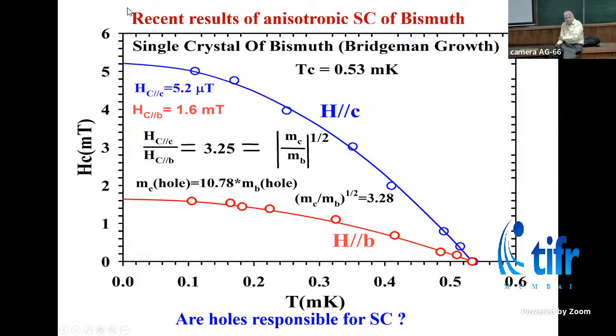What we have done in the last 2 years, I think before I took over as director, is the anisotropy. That was really hard because OHM has left. There was only one scientific officer with me, and we were doing the experiment. It took us 2 years to finish this part of the graph, which I told you about. So we see an anisotropy, and this anisotropy temptingly suggests that holes may be involved in the superconductivity. But we have to be careful because bismuth has a large spin-orbit coupling, which also gives rise to this anisotropy. So I have dumped this problem with Rajdeep. I hope we will get something out of it for Nature Physics soon.